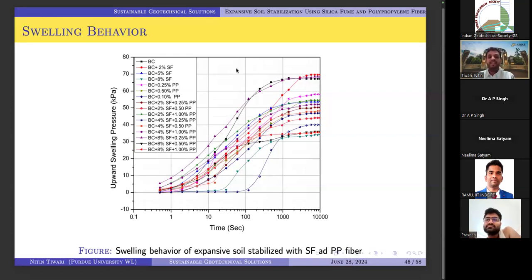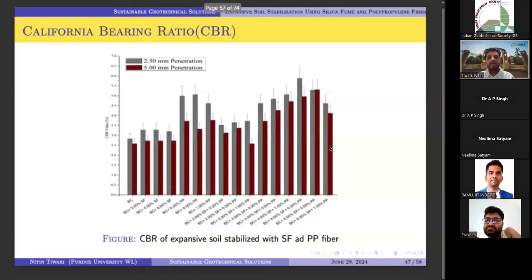So swelling behavior, you can see again, from the top, we reduced from 60-70 kPa to 30-40 kPa. With this treatment, we observe the CBR, and you can see an increment in the CBR values as well.